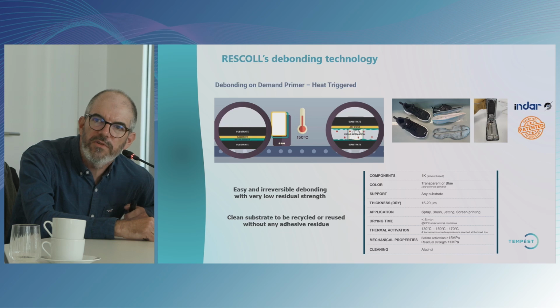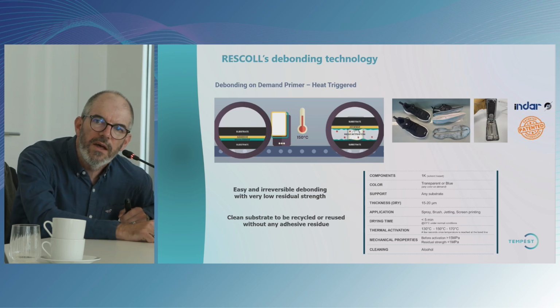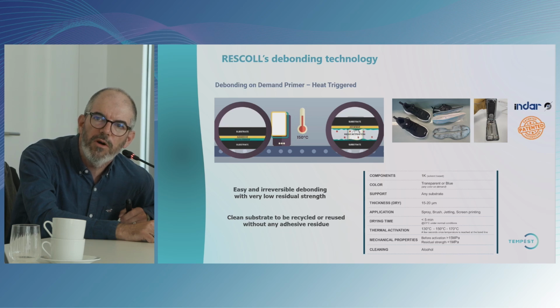It's easy and non-reversible, meaning that once you trigger in a good heat range, you can cool down the parts and separate them easily. And the substrates need to be clean, so we have very few primer residues, and they can be wiped off with alcohol. We can reach very high strengths because for some applications we can be higher than the 20 MPa range.